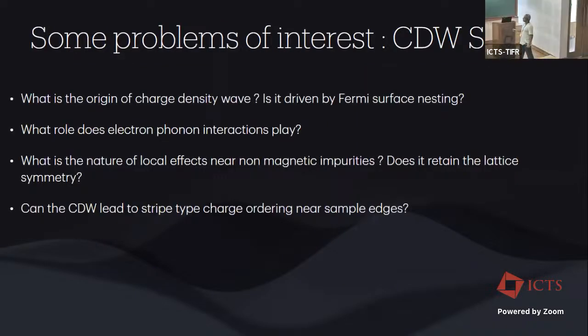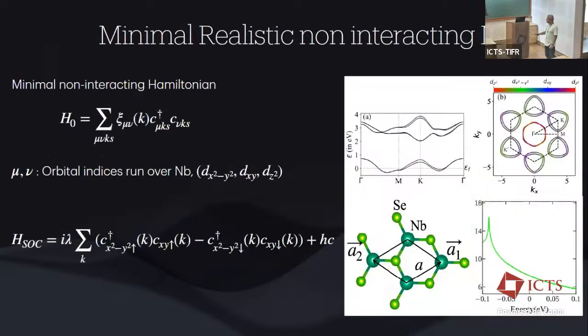So these are the questions. I won't read them. You got the basic idea that there is a question first because of the large enhancement of the CDW transition temperature. What is the mechanism for the formation of CDW? What role does electron-phonon interaction play in the system? What is the nature of local effect near non-magnetic impurities? Does it retain the lattice symmetry, for example? And can the CDW lead to stripe-type charge ordering near sample edges that you saw in the experimental measurements?